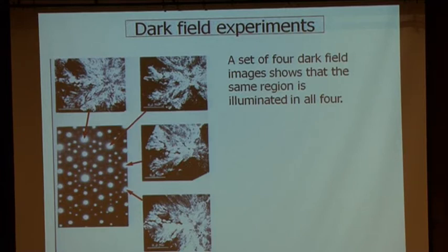So you can have one bright field image and many dark field images. Okay? So these are dark field experiments using different beams, and on the left-hand side, you see the diffraction pattern, and the beams that were used for dark field experiments are marked. And I was hoping to see those twins, but I could not see any twins in any of these dark field images.